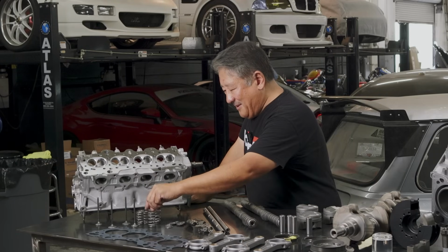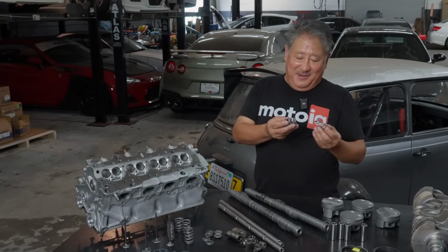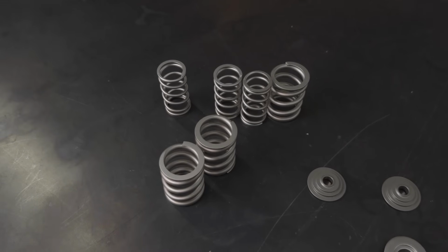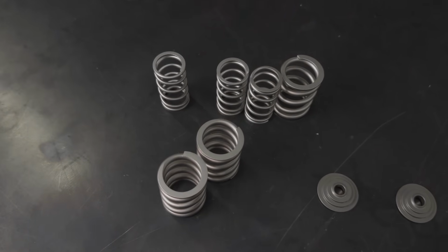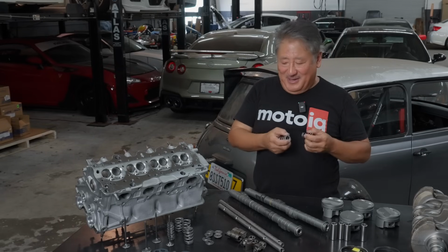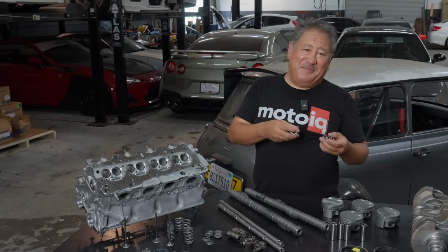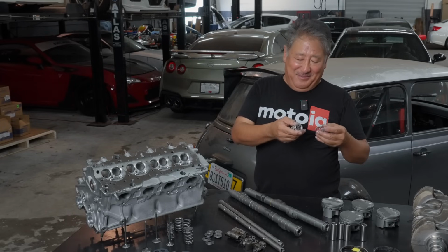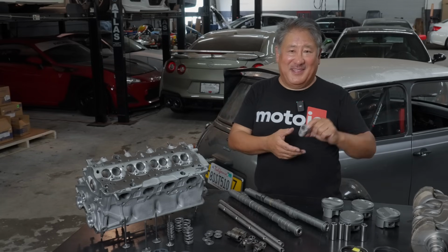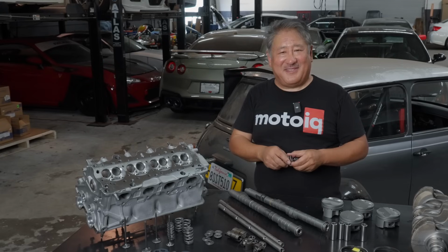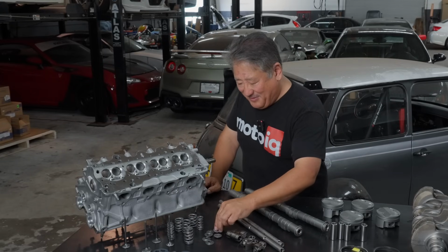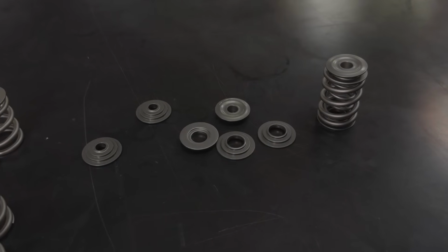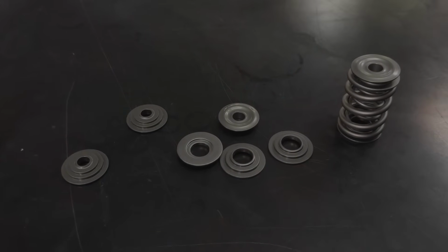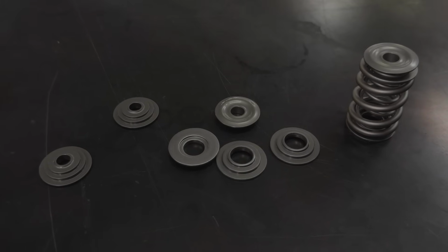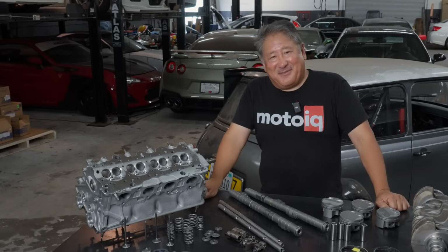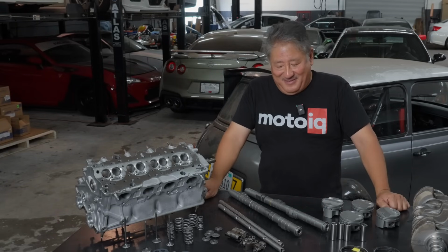Now you look at the Kelford spring, it's made out of a really high grade wire. They're shot peened after manufacture, and the inner spring is an interference fit with the outer spring. Now this interference fit works to damp harmonics, and you see sometimes the inner spring's just rattling around, but in this case there's actually contact between the inner and outer, which acts like a damper, which reduces the chances of surge. The springs also have a precision valve seat that really locates the inner spring, and a titanium retainer that's lightweight, wear resistant, and you don't want to have excessive reciprocating weight because that can lend itself to spring surge in itself.